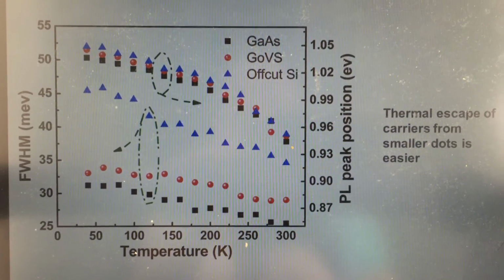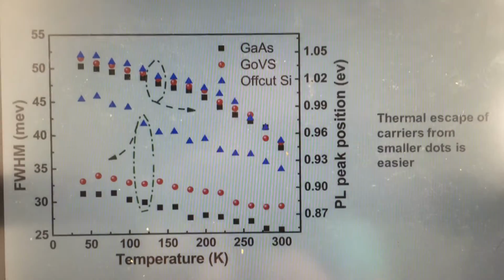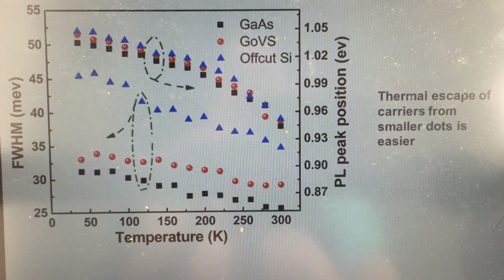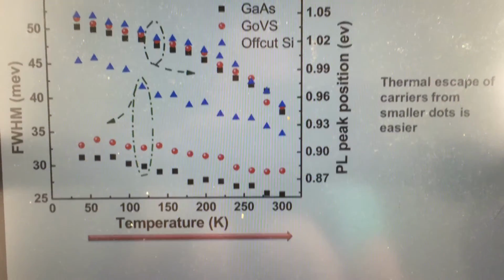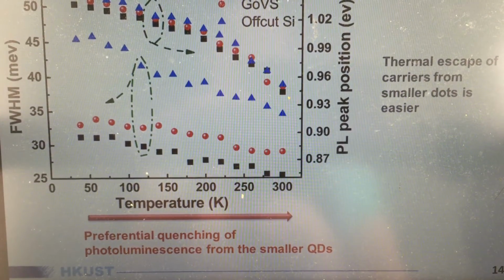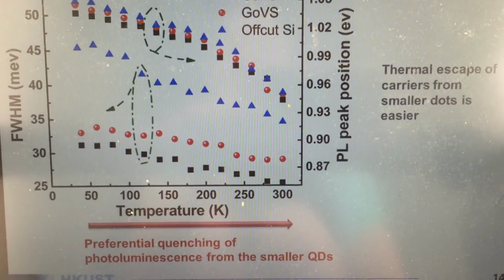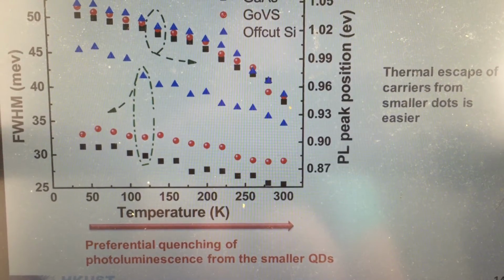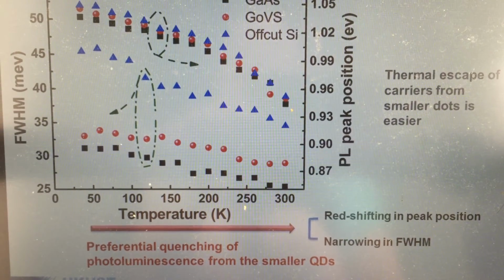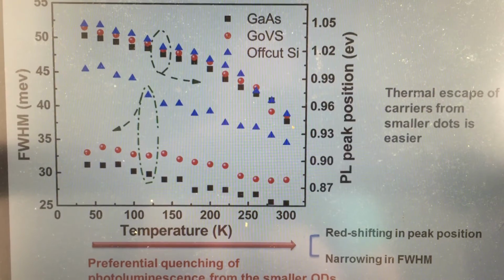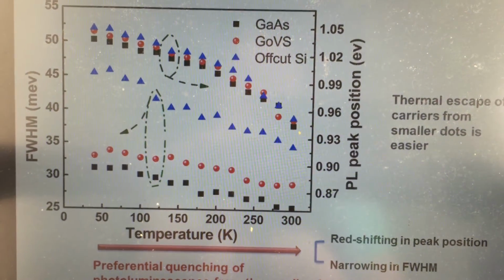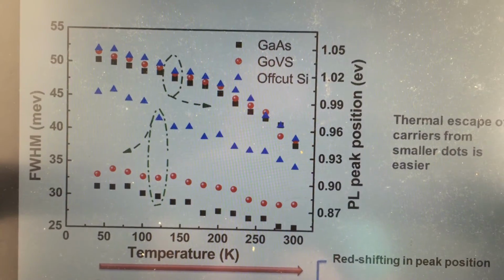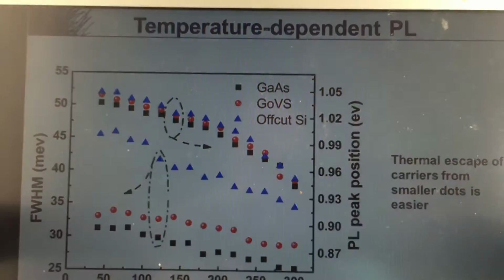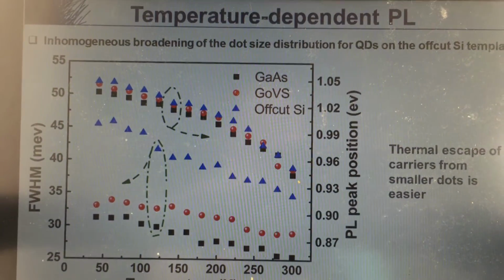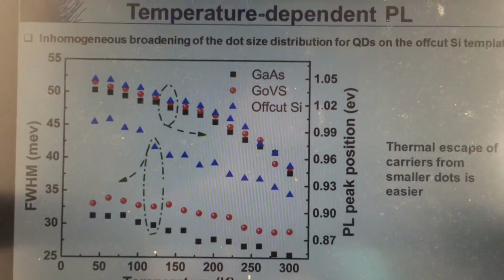As to the temperature-dependent full width at half maximum, we know that the thermal escape of carriers from smaller dots is easier compared to the larger dots. So, as temperature increases, there will be a preferential quenching of photoluminescence from the smaller quantum dots as compared to the larger dots. This leads to the redshift in peak position and a narrowing in full width at half maximum. It's worth mentioning that the value of the full width at half maximum on the off-cut silicon template is always much higher than the other two, which indicates a more serious inhomogeneous broadening of dot size distributions for quantum dots on the off-cut silicon template.